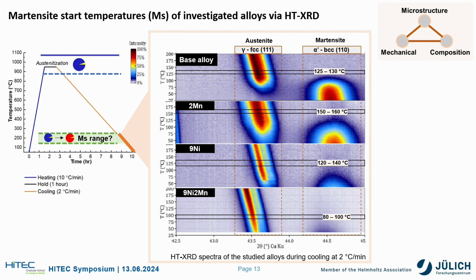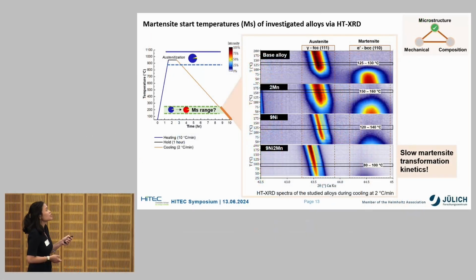Notably, for the 9Ni2Mn, we see slow martensite transformation kinetics, and therefore austenite remains retained and predominant at room temperature. So we can make a big check here in terms of achieving the microstructural requirement for the target 304 steel.